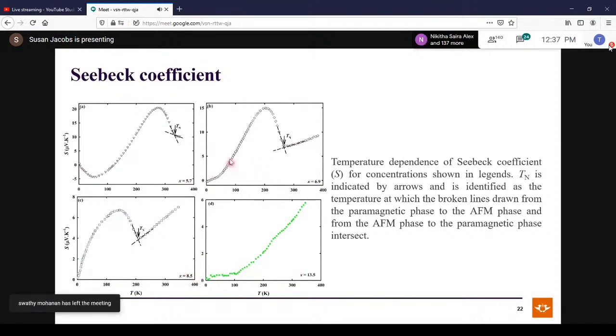Okay, and here to locate Tn, we took the point at which the broken line in the antiferromagnetic region intersects the broken line from the paramagnetic region, where the two lines intersect. We took that as Tn. And once again, there is good correspondence between Tn obtained from Seebeck coefficient measurements with electrical resistivity as well as magnetic susceptibility measurements.